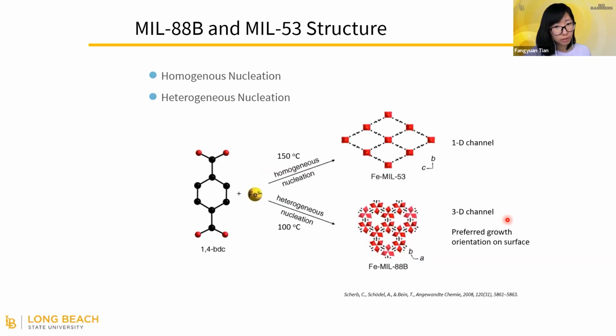But when we did the synthesis, we noticed that MIL-88B is not a material that is easy to synthesize. You have to be very careful about the temperature. If the temperature is too high, you will not get MIL-88B. Instead, the terephthalic acid and iron will go through a homogeneous nucleation, and this time you will get MIL-53, which has a one-dimensional channel, versus MIL-88B, which has a 3D channel and a preferred growth orientation on the surface.